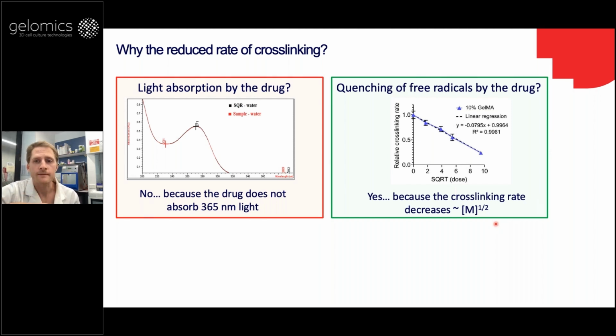But this couldn't be the case in this case, because the drug doesn't absorb at that wavelength. You can see here the UV spectrum of the cefazolin, and the 365 is around here, so there's no absorption. But another idea is that the cefazolin might be actually quenching the radicals that are being generated when the photoinitiator